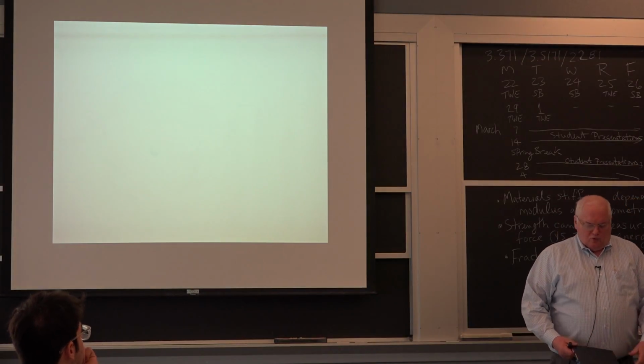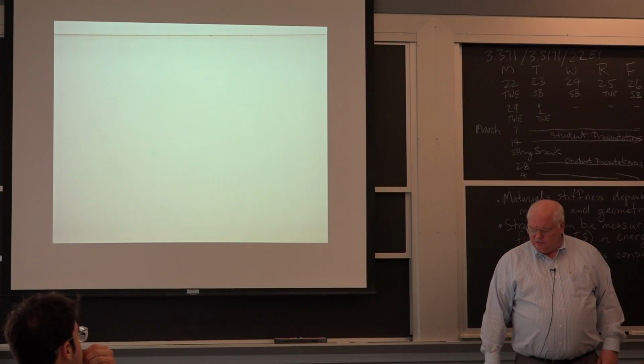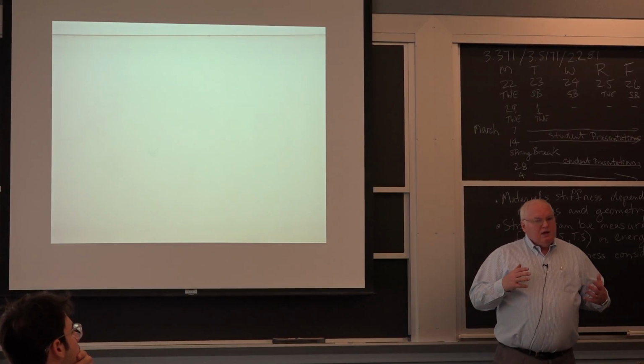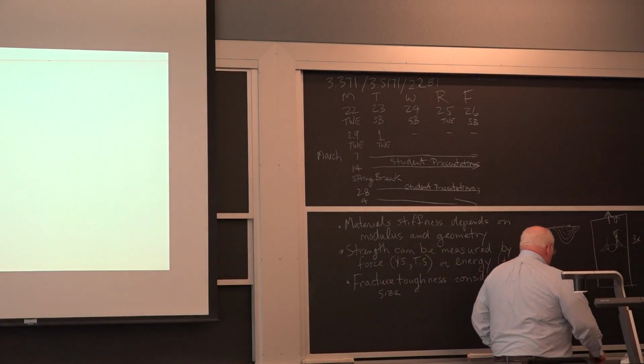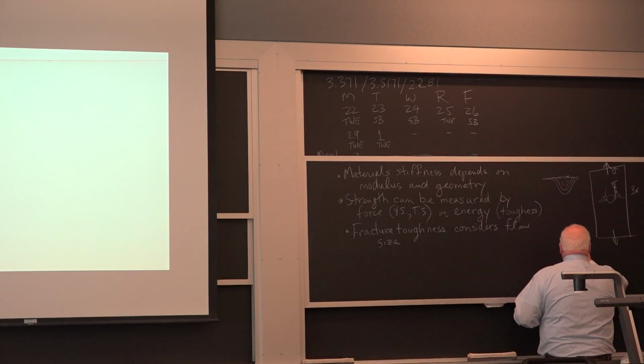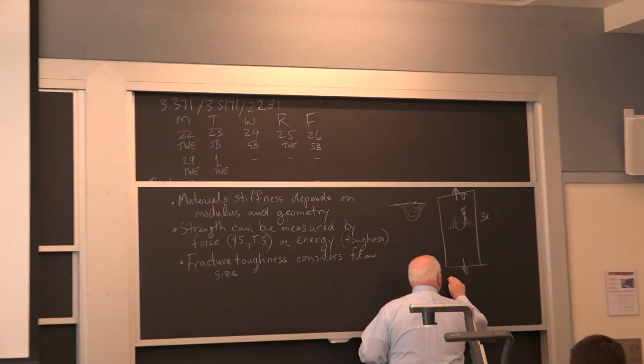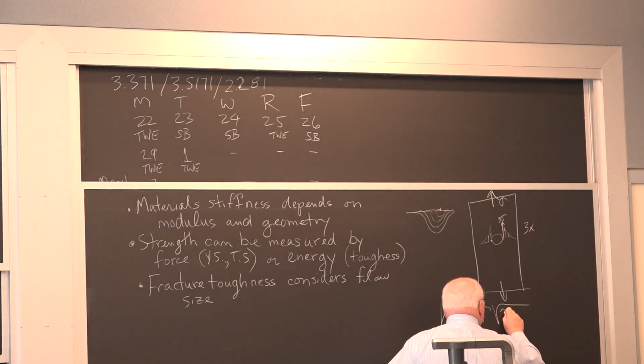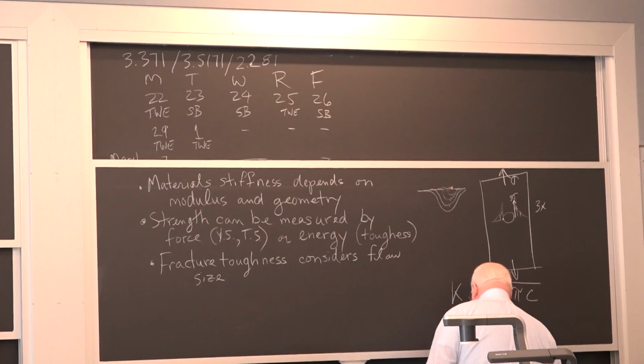There were 3 places where they did big studies of brittle materials after World War II, even though Griffith had explained the brittle fracture of glass, but no one understood why he was studying glass and fracture. Everyone knew it was brittle. But Griffith had explained it was the flaw size, and he came up with the fundamental equation of fracture mechanics, which I wrote down the other day: the toughness of the material must be greater than the applied stress times the square root of pi times the crack length.